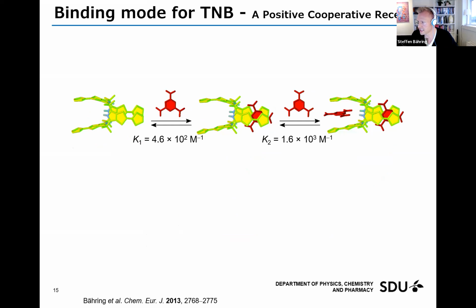Going back to the complexation with the nitroaromatic explosives such as TNB, we have also been able to derive the stepwise binding, and this is interesting because the TTF Calixpyrrole is flexible and dynamic, and it doesn't exactly retain the 1,3 alternate conformation, but it has some flexibility to it. But upon binding the first TNB molecule, then it pre-organizes the second binding site.